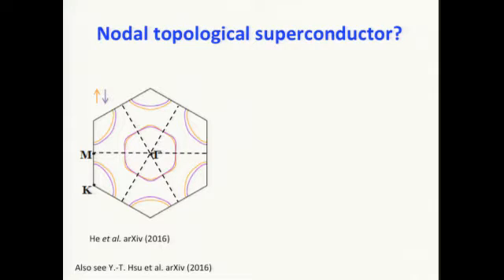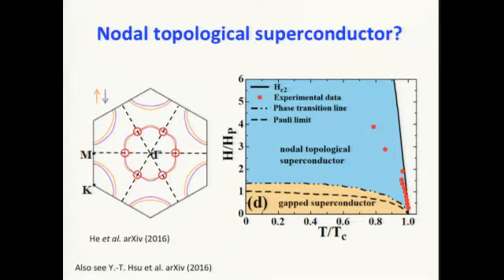in this material. So here is the Fermi surface, and I mentioned that because of spin-orbit interaction, the Fermi surface is spin split, except there are actually several points on the Fermi surface at the gamma point, whose effect I have so far ignored. Actually, it has been calculated that when you apply a magnetic field in this material above the HP but below the upper critical field, the material turns into something called a nodal topological superconductor. You can think of it in this way: at these several points, the superconducting gap is not protected by spin-orbit interaction because the spin-orbit field is zero. So the gap would just close at these several points here.